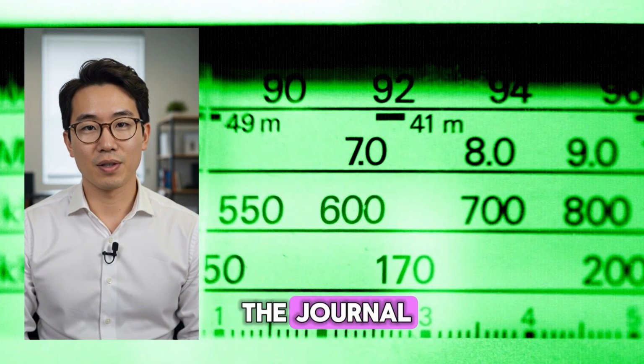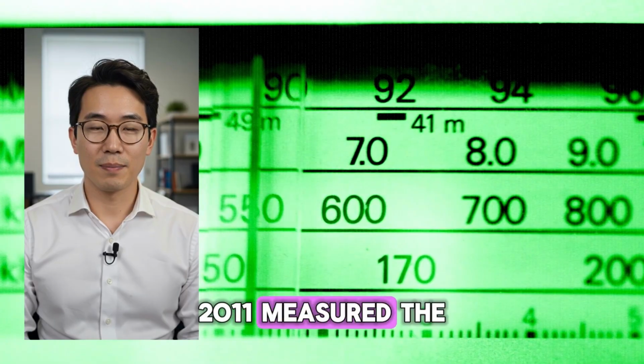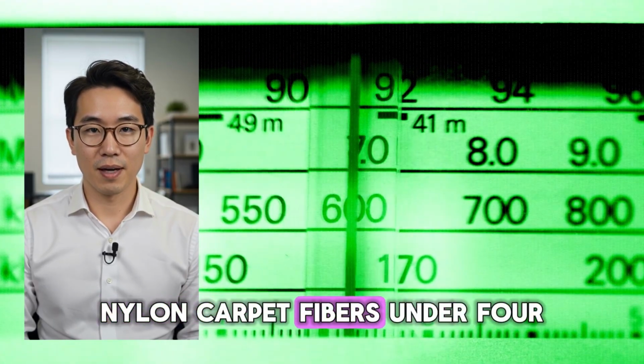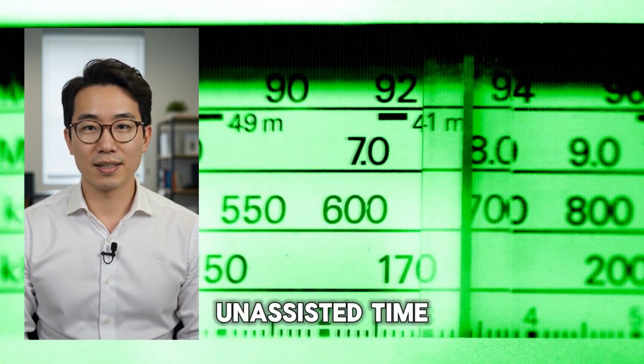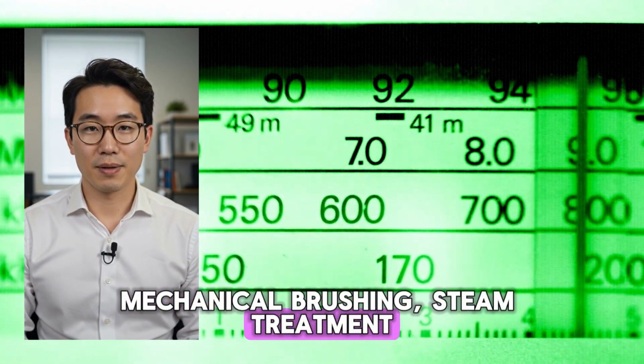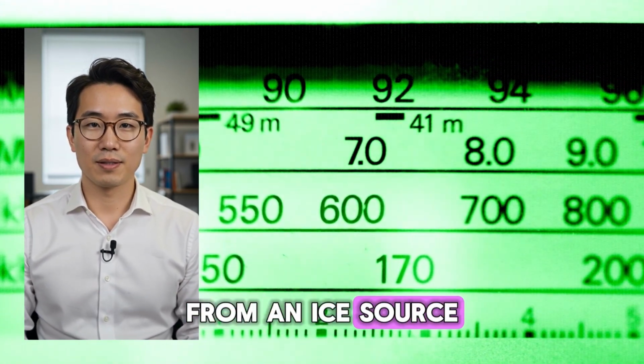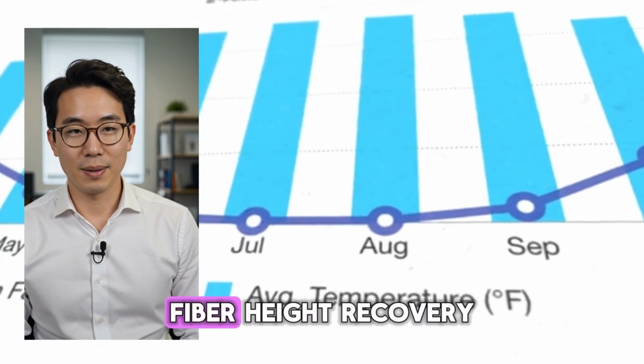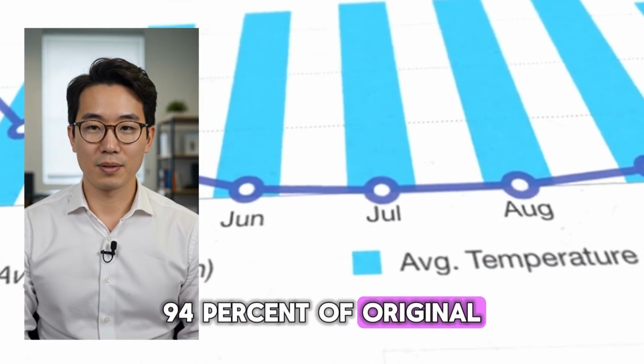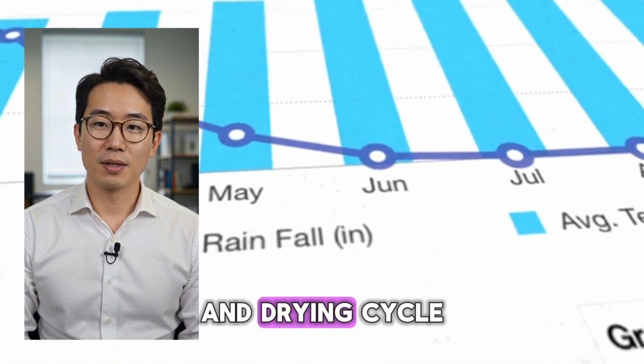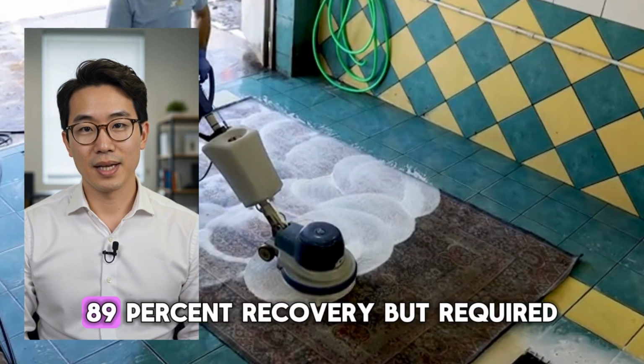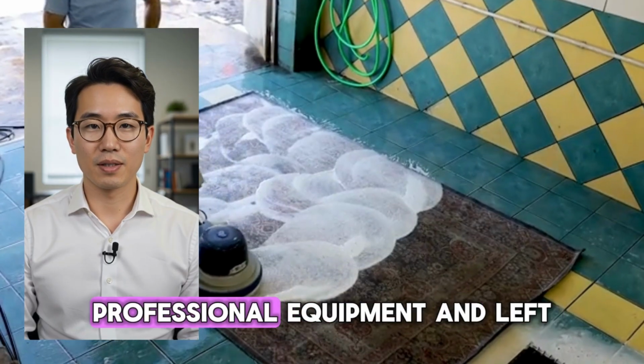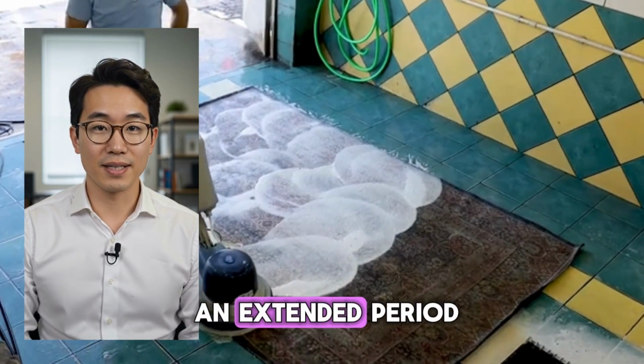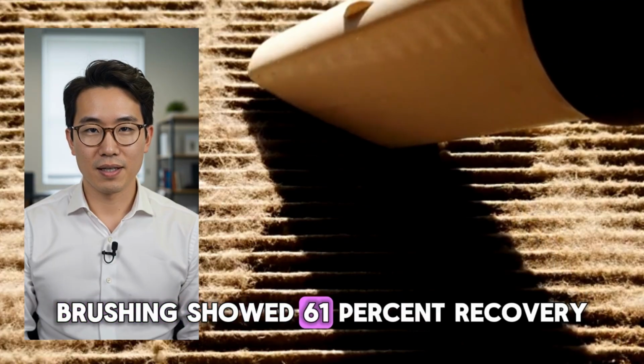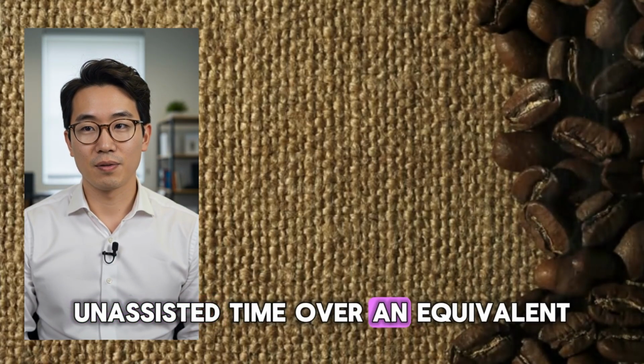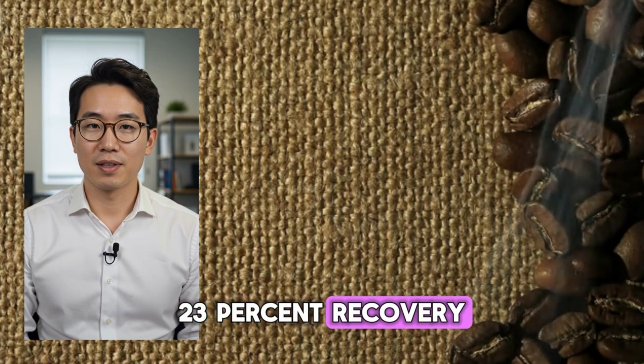A study published in the journal Textile Research Journal in 2011 measured the recovery of compressed nylon carpet fibers under 4 conditions: unassisted time, mechanical brushing, steam treatment, and controlled wetting and drying from an ice source. The ice wetting condition showed the highest fiber height recovery, 94% of original pile height, after a single treatment and drying cycle. Steam treatment showed 89% recovery but required professional equipment and left the carpet damp for an extended period. Mechanical brushing showed 61% recovery. Unassisted time over an equivalent period showed 23% recovery.